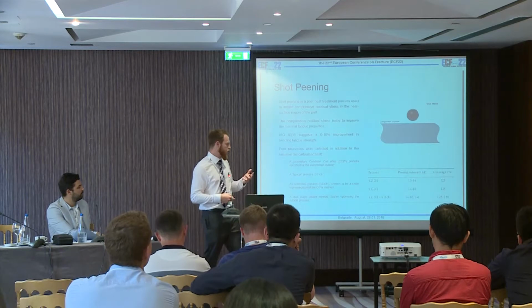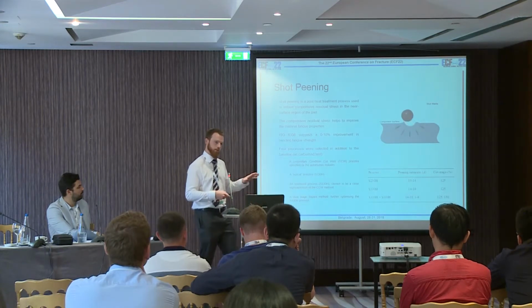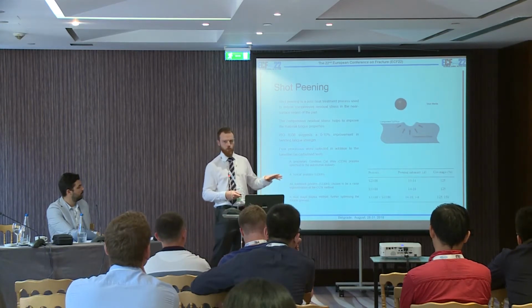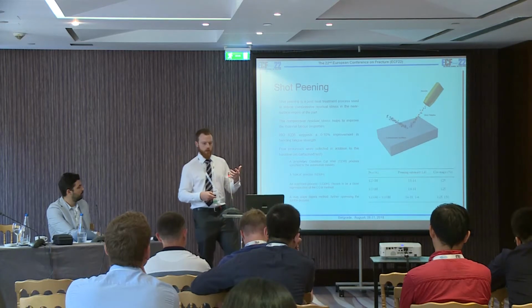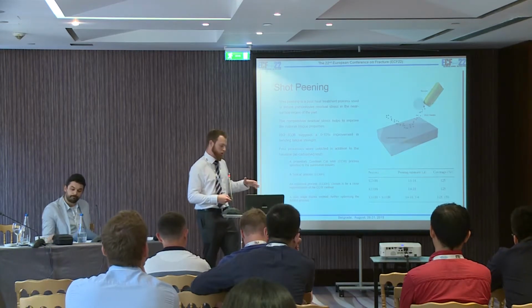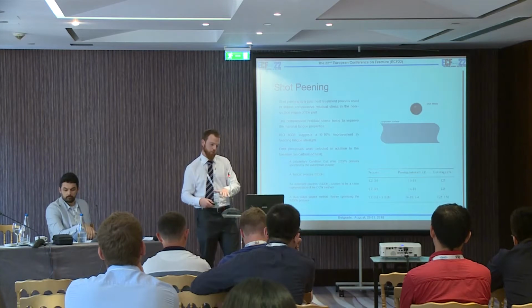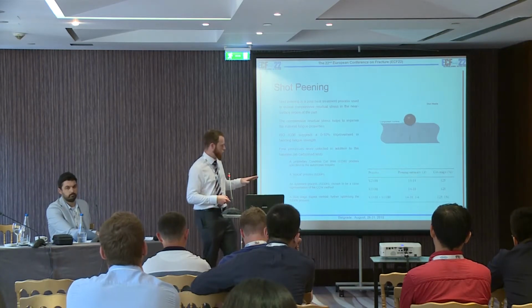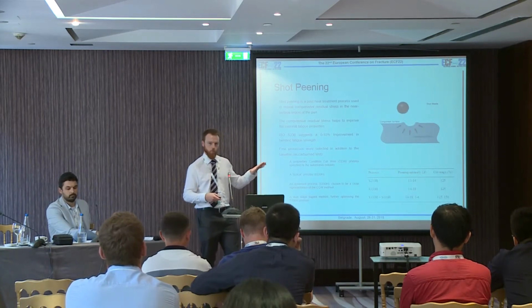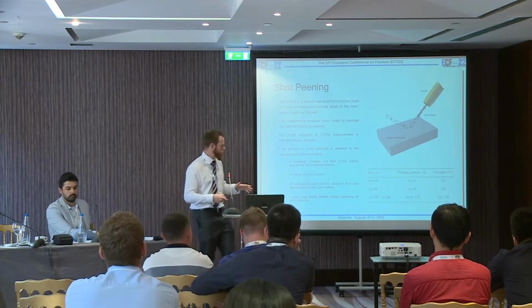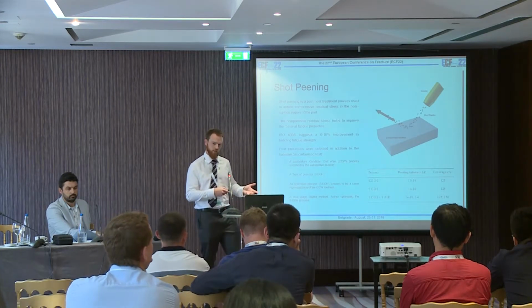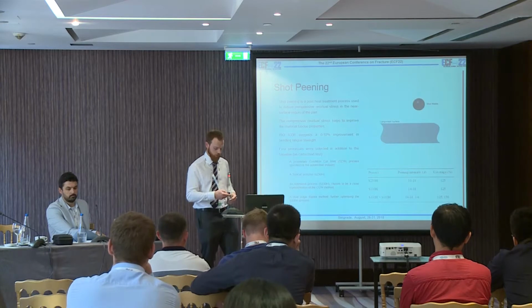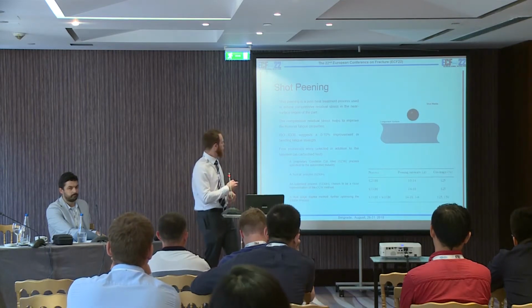We then looked at a fourth process, which was optimizing that further using a duplex shot peening method. So you use a larger shot to start with, which should induce compressive residual stresses deeper within the material, and then we use a smaller shot, which should give us nearer-surface benefits. We did also then test, of course, baseline material as well, so you'll see the baseline data too.